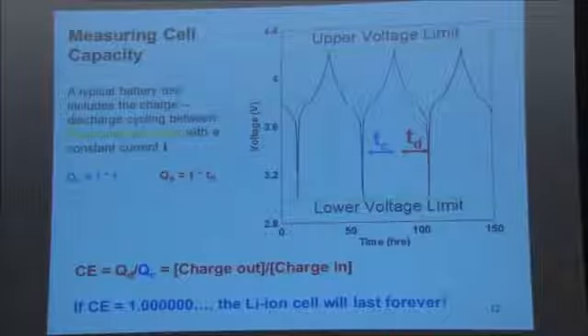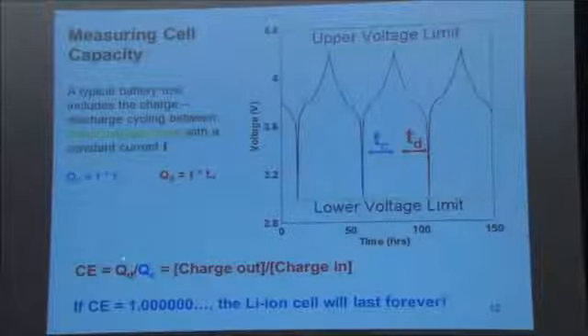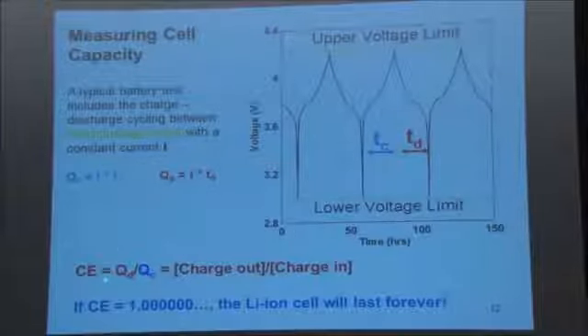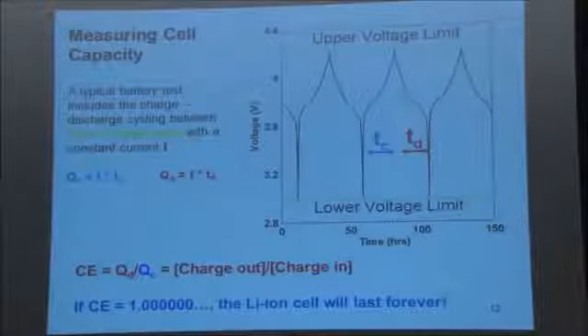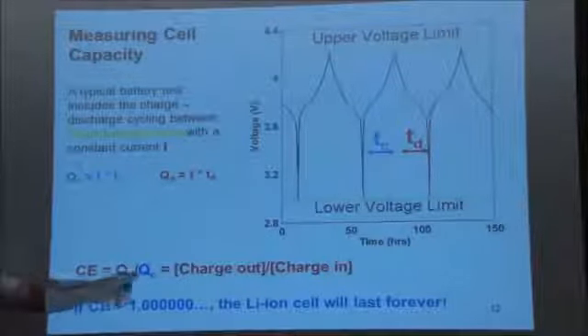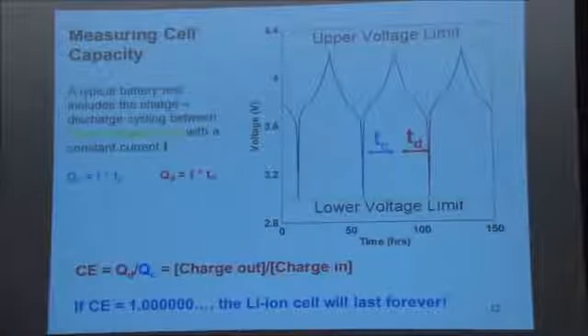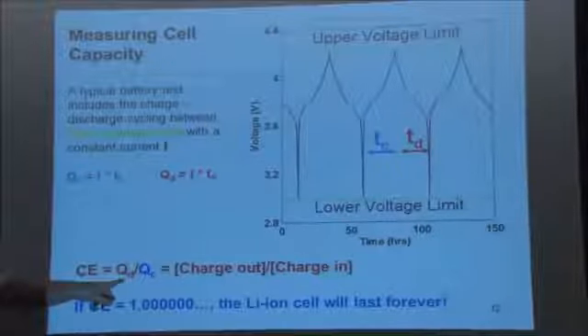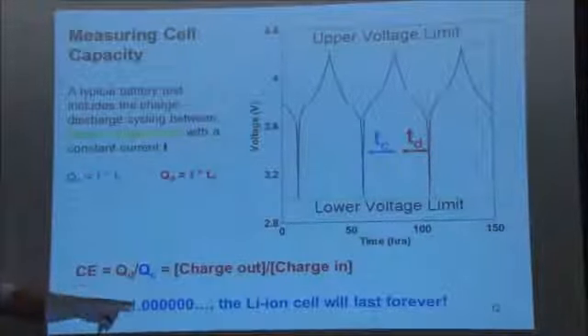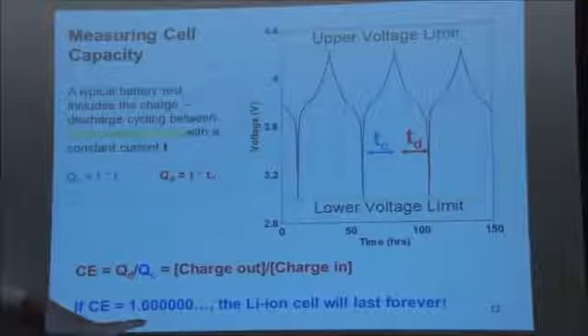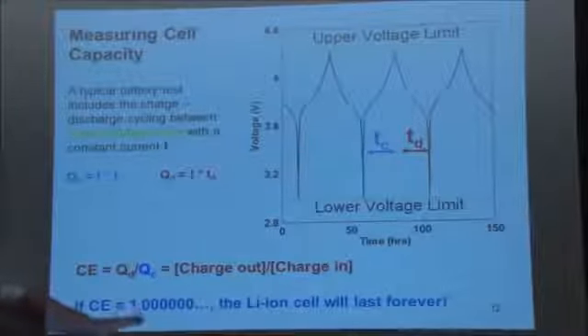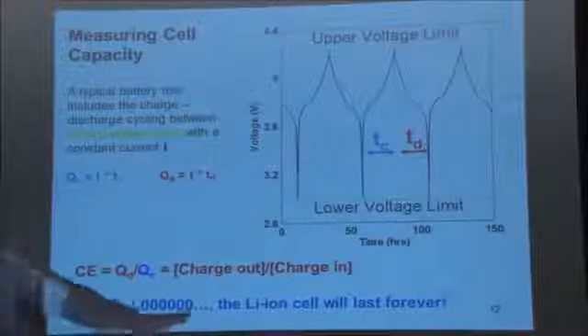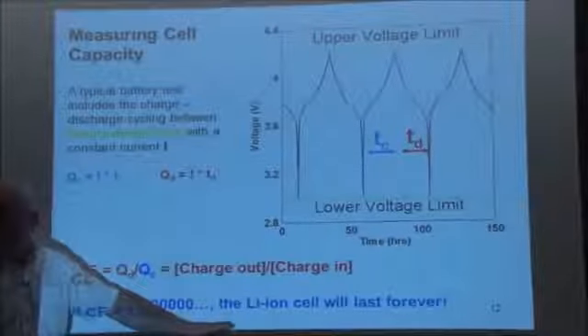And for a perfect lithium-ion cell, the charge the cell delivers and the charge that you store in the cell during the charge should be exactly the same. So this ratio, the Coulombic efficiency, the ratio of the charge the battery delivers to that which you store, should be exactly 1. And if it is exactly 1, the lithium-ion cell will last forever.